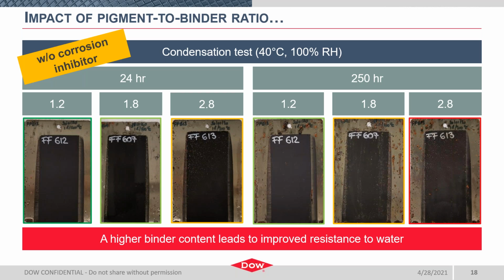So in other words, as you decrease pigment to binder ratio, you improve the water or humidity resistance in this case. And this is mostly expected, confirming that the PVC of the paint can significantly impact the porosity of a coating film. Of course, this is always going to depend on other formulation parameters, but this optimized pigment loading level is represented in that starting point formulation that I shared at the beginning of the webinar.